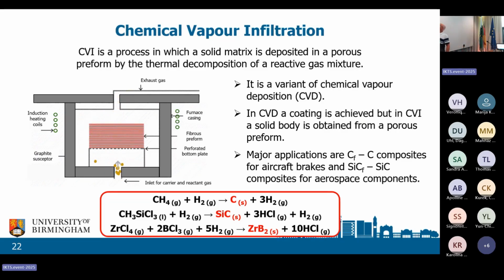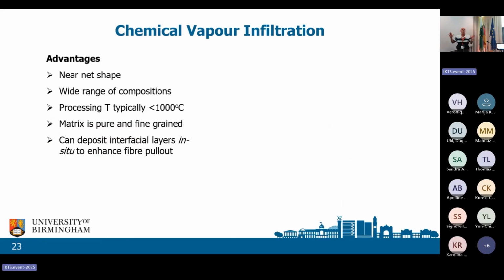And for silicon carbide, SiC composites being used for aerospace. So the process works. There's all sorts. You can use methane to give you carbon. You can use trichloromethylsilane to give you silicon carbide. You can even use, and we have done, zirconium chloride and boron chloride to give you zirconium diboride. So there's a lot of possibilities that you can use there. So the advantages, it's near net shape, wide range of compositions. Processing temperatures are beautifully low. No more than about 1,000 degrees centigrade. No damage to your carbon fibers. The matrix you get is pure and fine grained, which is great, gives you good strengths. And you simply put one gas through and there's your interfacial coating, and then a different gas and there's your matrix. So terribly efficient in that respect.